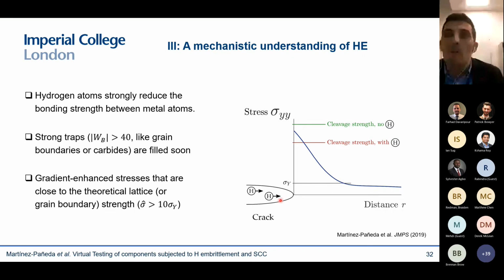However, the moment you bring hydrogen into the picture, those grain boundaries are going to be full of hydrogen. You're going to drop your cleavage strength by 20, 30%. And then your stresses, when you account for those dislocation hardening mechanisms, those stresses that you get at that critical distance are big enough. And these two lines cross, and then you have a story. You have a rational interpretation, a mechanistic interpretation of how you go from a ductile fracture process to a brittle fracture process. And the good thing is that you have that without any fitting parameters whatsoever.